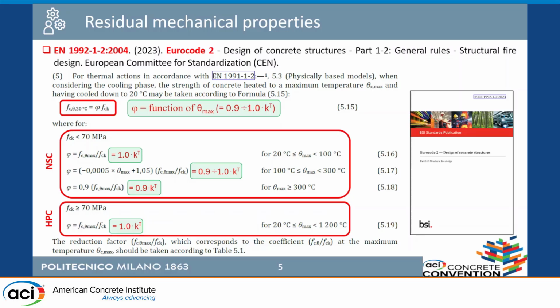In general, as you can see here, in this square, we have what is referred to the normal strength concrete, and here to the higher grade concrete, so we can say HPC. You see that KT is the decay of the strength with the temperature, while phi represents the further decrease because of the cooling phase. You see that this coefficient in the end is between 0.9 and 1. So in the end, the Eurocode is more or less saying that in the residual condition, we have almost the strength related to the maximum temperature reached in that point.